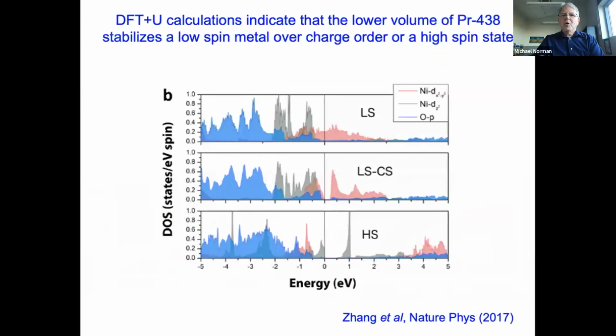So what we were able to show is, in fact, with DFT plus U, this is a calculation that Antia did, that the low spin metal state and the stripe state are very close free energy wise. It's very easy to go from one to the other. And people had originally thought 10 years ago it was a high spin state, but we now know that in fact it's not. You either get a low spin stripe state or a low spin metal state, and they're rather close in energy.